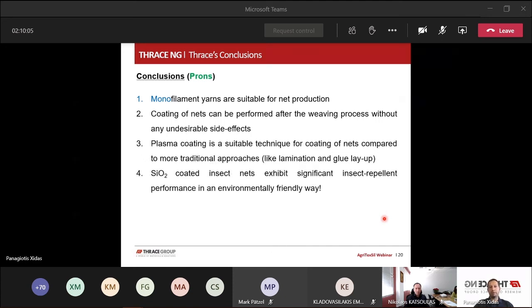Coating of nets can be performed after the weaving process without any drawbacks, any side effects. Plasma coating is a suitable technique for coating of nets compared to other more traditional approaches like the hot melt lamination and the glue layup. And the SiO2-coated insect nets exhibit significant insect repellent performance, as the Professor showed already, in an environmentally friendly way, which was the scope of this project.